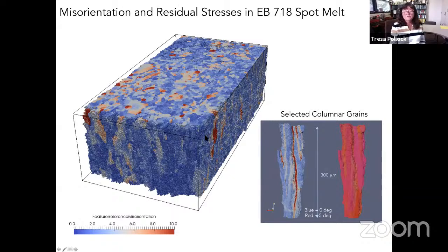Here are some other sorts of things that we've been able to learn about the process. If you take the columnar grain data set that I showed and look at the misorientation in 3D. We all know that cracking and residual stresses are a major challenge. And what one can see from the 3D EBSD data is the buildup of tremendously large misorientations. And these are the locations where one might expect a crack to develop eventually.